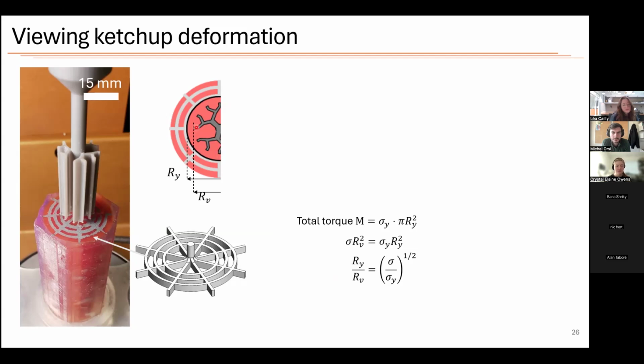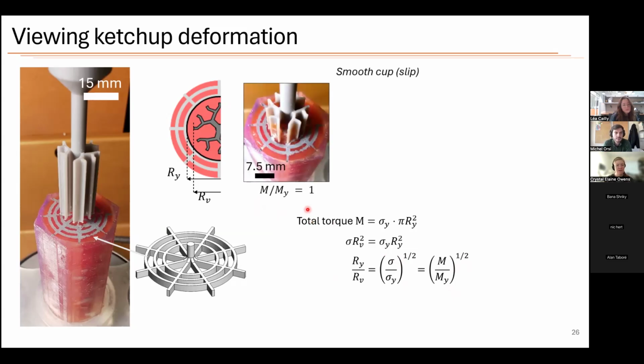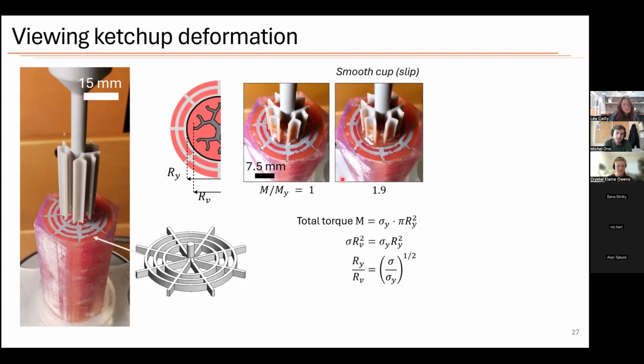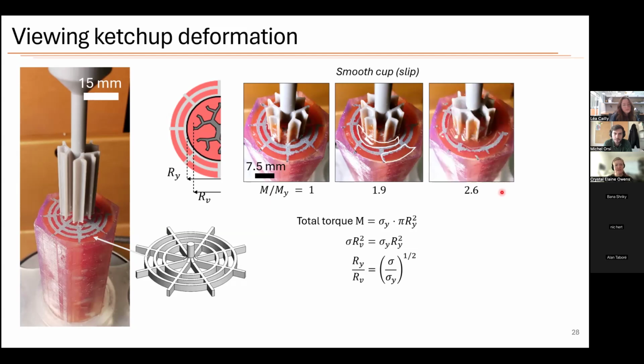So as you increase the torque, and this is also equal to the torque over the yield torque. If we have these equal to 1 and the vane is rotating, you can see that the target remains undisturbed and the vane is just in place. As we increase this value, we start to get some of the material displaced around the edge. And then we also see some slip around the outer wall. This is where these lines, instead of being straight, start to bend. And then as we increase this even more, these same effects occur, but even more dramatically, where here slip is so large that the target on the outer surface is starting to become destroyed.